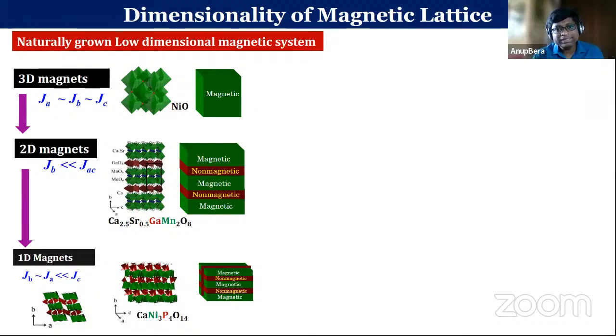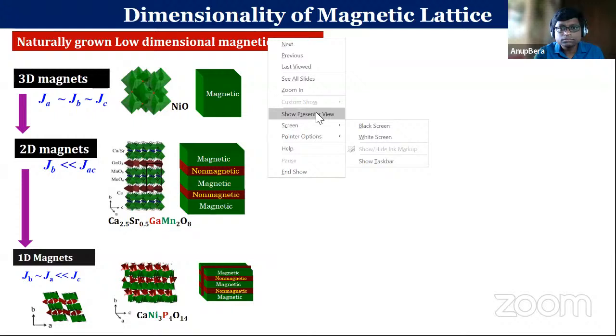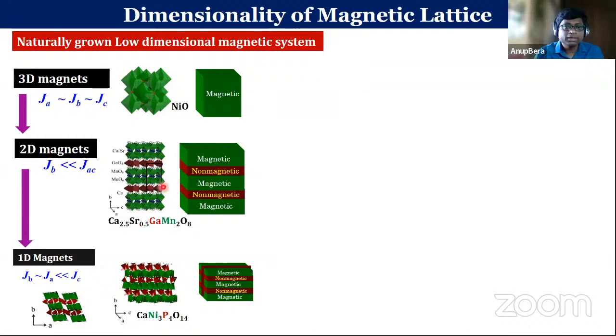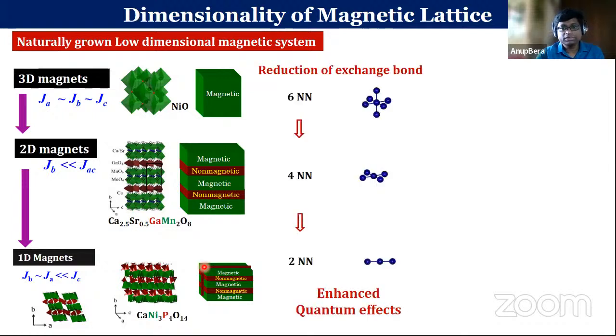But if we put a non-magnetic layer like here, then we make 2-dimensional lattices of magnetic ions. For example, this is a real compound. If we look at the crystal structure, we see the green layers are magnetic. They are well separated by the non-magnetic gallium layers, and they effectively show 2-dimensional behavior. Similarly, we can get 1-dimensional magnets based on real 3-dimensional crystals, where the magnetic ions are arranged in a chain. And today's talk is especially about this 1-dimensional magnet.